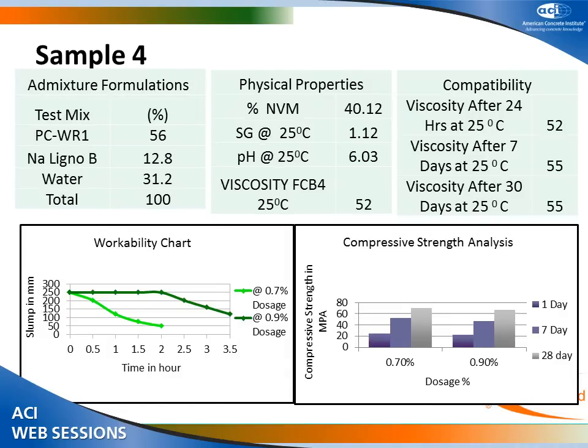Sample 4 is again, now we have reversed the combination. We have 75% of the PCE and 25% of the sodium lignosulfonate, again from the South African origin. And you can see that the workability has been retained almost up to 3.5 hours at 0.9% dosage. And even at 0.7% dosage, around 1 hour retention is possible. Compressive strengths are again around 64, 65 with 0.7% dosage, and around 62 to 63 at 0.9% dosage.